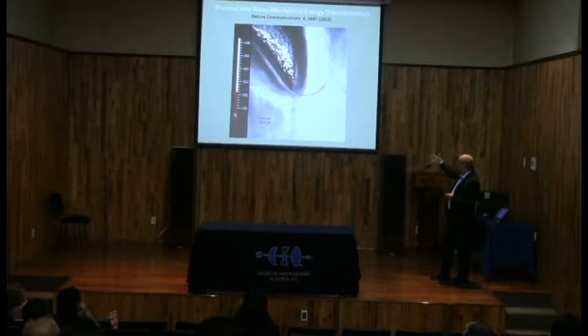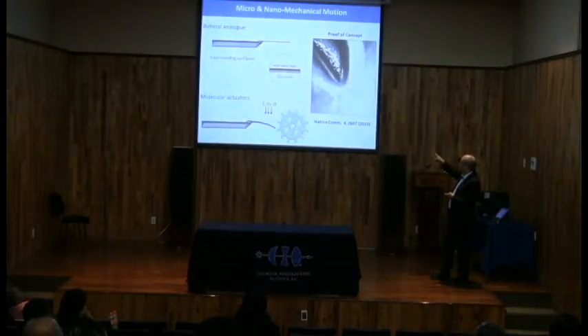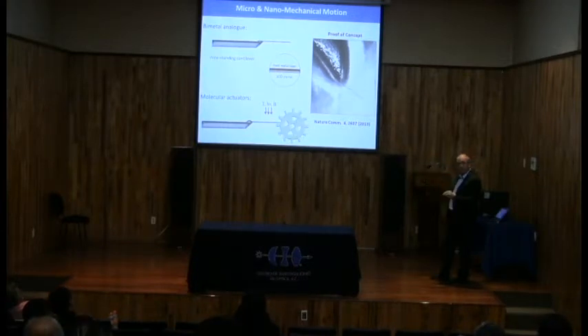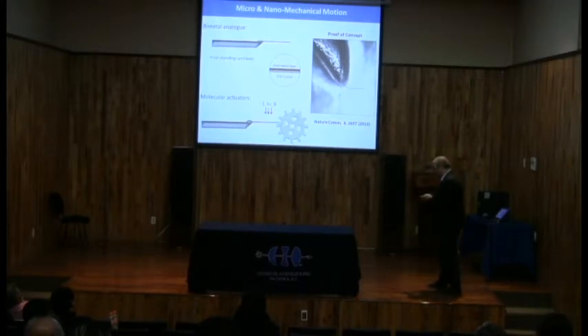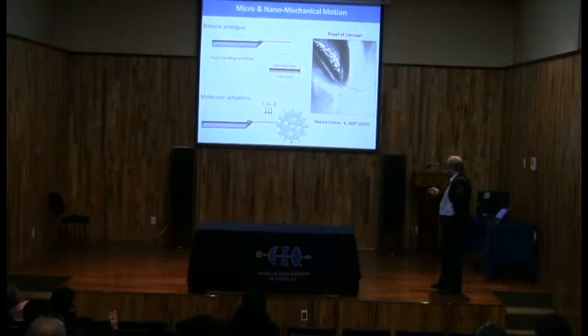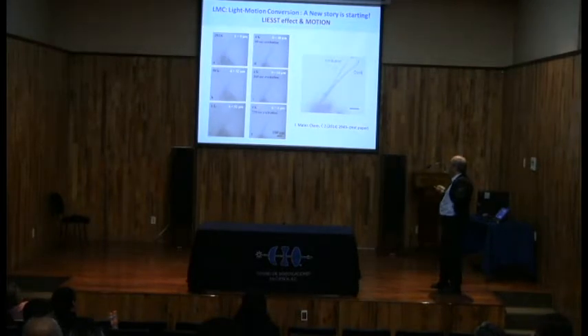What is important here is that you can control the direction of the motion by changing the temperature. And then, of course, the idea is the following: by having this actuation as a function of temperature, light, or magnetic field, you can generate controlled motion. Okay, that means that you are converting energy, thermal energy or light energy, into motion in a controlled way. So then, of course, we tested this experiment as a function of light. You see, dark and irradiation, you have your actuation.